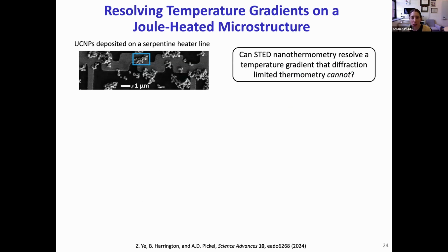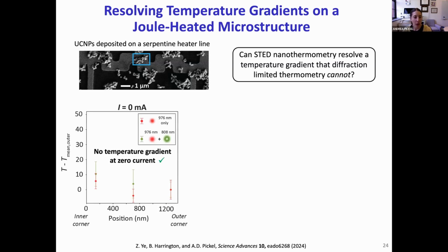We found it was very challenging to get self-assembled UCNP monolayers to land exactly where we needed them. We had more success drop casting UCNPs onto the heater lines. And here we got a cluster of UCNPs that spans the diagonal from the inner corner to the outer corner for one bend of the serpentine. So let's first look at the control case of zero applied current. What I'm plotting here is the temperature rise at 3 locations relative to the temperature at the outer corner. And as expected, with no applied current, the data points are essentially flat, meaning that we don't detect a temperature gradient for both diffraction-limited and STED measurements.